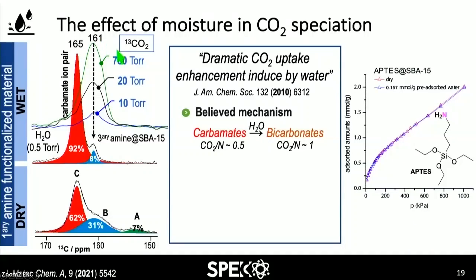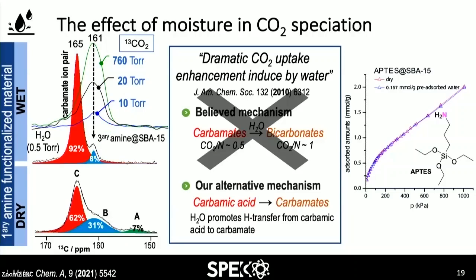If you compare, this is an overlay of a tertiary amine with the exact same material, the SBA15, and you can see here with distinct amounts of CO2, you can see that there is a species formed at 161. Why do we compare the primary amine with the tertiary amine? Because in tertiary amine, you only have the formation of bicarbonate. There is no other species. So our hypothesis is not that the increase is due to bicarbonate.